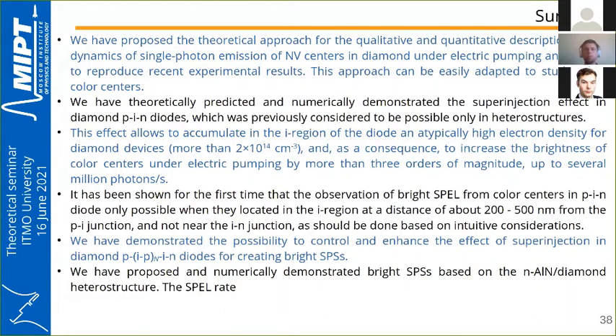We have also proposed the possibility to control and enhance the effect of superinjection in diamond p-i-n diodes, and we have proposed and numerically demonstrated bright SPS-based single-photon sources based on the aluminum nitride-diamond heterostructure, and yes, the SPL rate can be as high as 3 million photons per second.